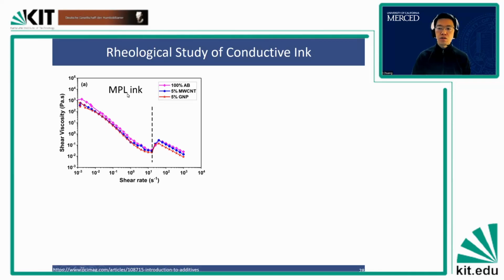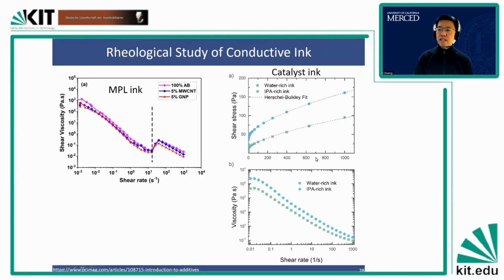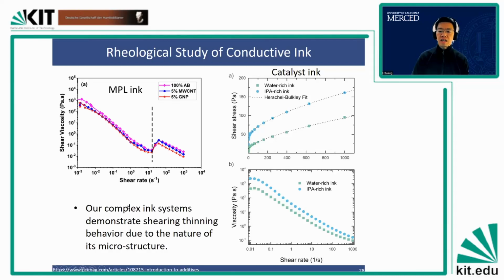So you can see this is referred to as our microporous layer, which has carbon and PTFE. And then on the right here is our catalyst ink, which has platinum carbon typically for low temperature PEM, and also has ionomer in there. And so you can see that both of them, if you look at this chart of viscosity as a function of shear rate, exhibit shear thinning behavior. When you have carbon, you have this transition area where there is a little bit of shear thickening, but then it continues to this shear thinning behavior here. Okay, and so we know that this ink is a complex ink that demonstrates shear thinning behavior.